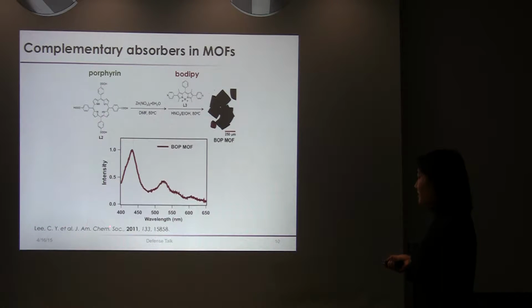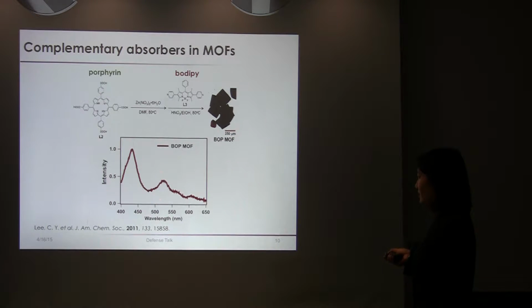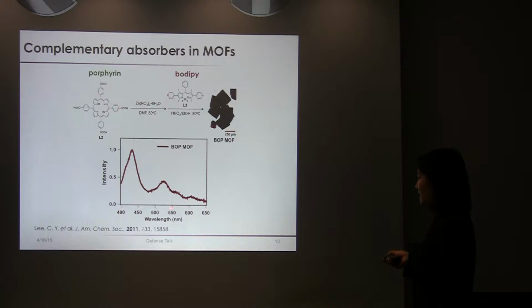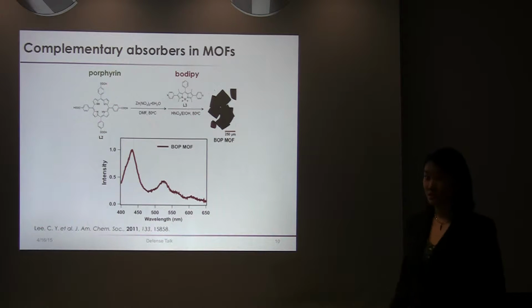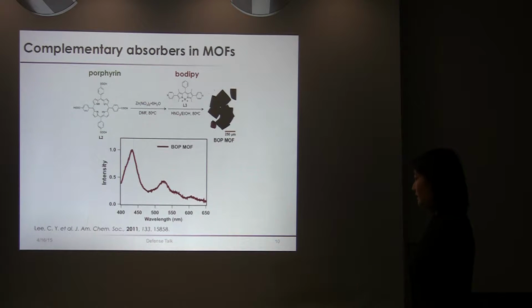And essentially, from the excitation spectrum, they saw that there was responsivity, not only with a high molar extinction coefficient in the blue, and also to a lesser extent in the red regions, but also the dye was able to fill in the spectral gap in the green regions. So this tells us that MOFs can essentially be used to harvest most of the visible light spectrum.